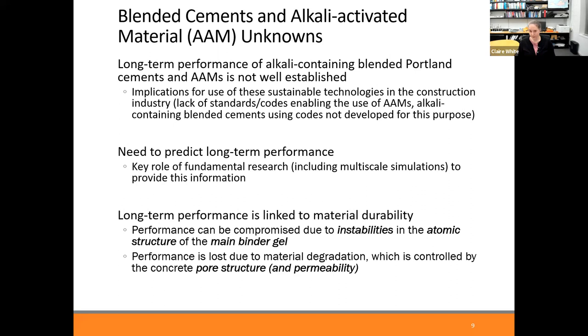And the long-term performance is linked to the durability of the material, how resistant it is to degradation. And this can be caused by instabilities in the gel itself. So understanding kinetics and thermodynamics is important. And also the pore structure of this material is very important, because there are aggressive chemicals that get into concrete and degrade it. And it's kind of funny, not everyone knows this, but carbon dioxide actually degrades concrete.